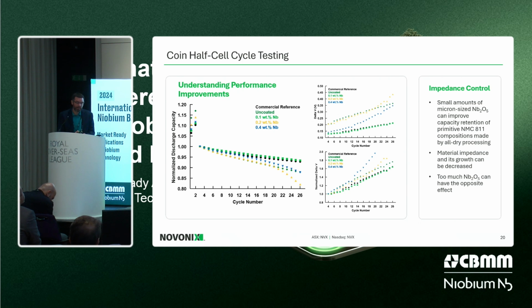Again, we see that the commercial reference as well as the 0.1 weight percent surface coating is very comparable and competitive. But then we start seeing that we do deviate from that line when we start adding too much niobium oxide on the surface. So really that is what is killing these cells, the higher impedance from having too much surface coating. And we can still optimize how we're putting the material on the surface. It's something that we can always play with, but it seems like we don't really need to go beyond 0.1 weight percent on the surface to have a very positive influence on the performance of this material.